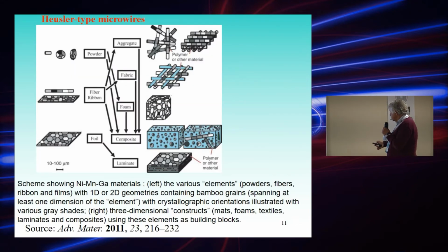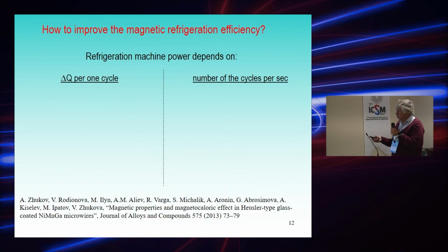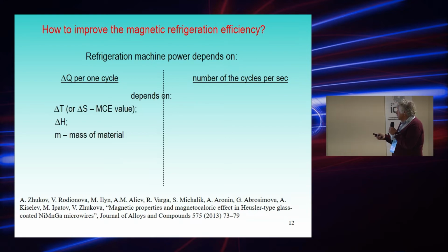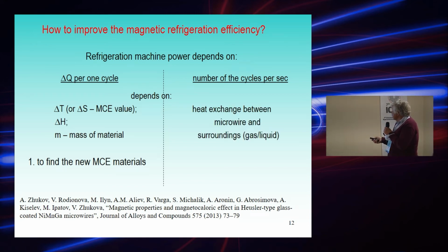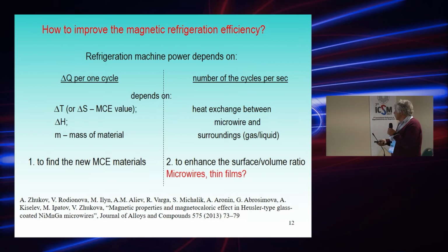Somehow the motivation of our job is this paper published in Advanced Materials, that low-dimensional magnetic materials could be useful for applications, for example, for magnetic refrigerators. So the refrigerating capacity depends on different factors. For example, one is the value of magnetocaloric effect, but another important issue is that these materials could have a higher surface to volume ratio, and this could enhance the heat exchange rate between material and the surrounding liquid.